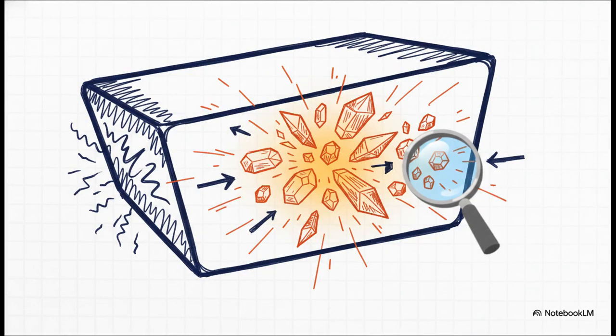And then there's the second combatant, transformation stress. And this is where it gets really wild. While the outside is rapidly cooling and trying to shrink, the crystal structure on the inside is actually morphing from its hot, flexible state, called austenite, into that super hard martensite. And get this, that transformation forces the steel to expand in volume. So you have a literal war going on. The outside is shrinking while the inside is trying to grow.